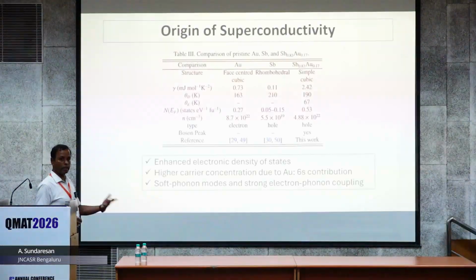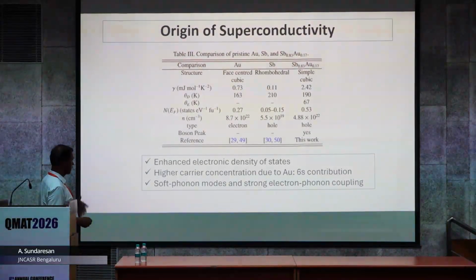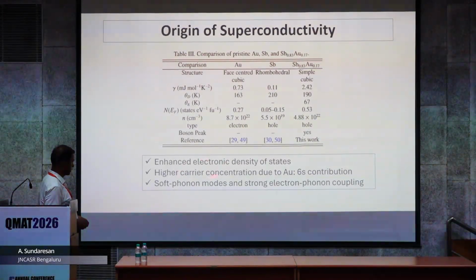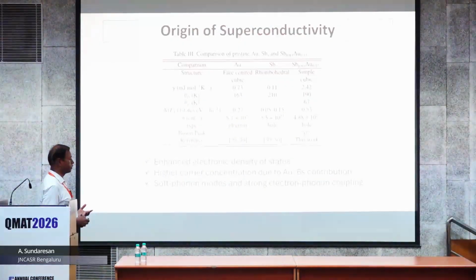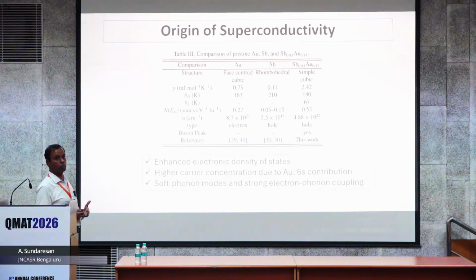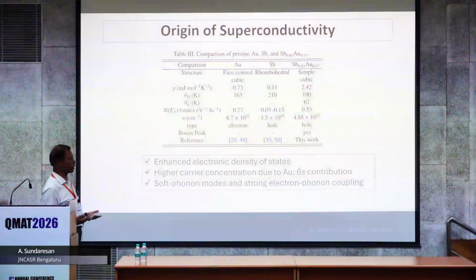Our studies indicate a possible large enhanced electronic density of states. This means the Au substitution modifies the antimony electronic structure and increases the density of states, and also increases electron phonon coupling, which is also responsible for the decomposition since this is not really a stable phase.